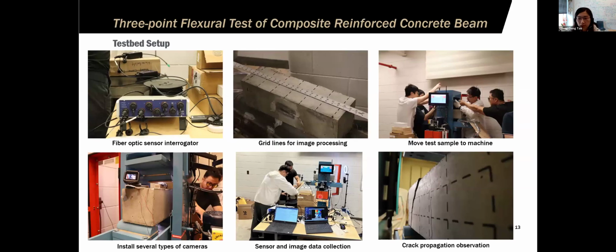So during the flexure test, we monitor the beam and collect the strain data of rebars and concrete using the sensor interrogator here in real time, and record the images and videos of the beam using different cameras like a GoPro, cell phones, DIC cameras. Here you can see we plotted some grid lines on the beam because due to the configuration of our compression machine, the front area was blocked by the machine. So we can only record the videos and images from the side view. So we use those grid lines to do the image conversion later.